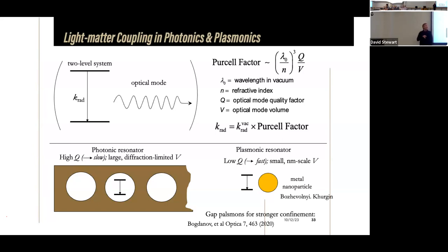But you still need to increase the coupling. And I could accomplish it by beating the diffraction limit, by taking the plasmonic structure, which could easily confine light down to 5 nanometers. 5 nanometers is 100 times smaller than the wavelength. And since you have to raise it to the power 3 because it's volume, it gives you a 1 million increase in the coupling efficiency just because of the confinement. And quality factor is 100. The bottom line is I have the same increase in the coupling efficiency, but if I use a plasmonic structure instead of a dielectric cavity, my system operates much faster, at the rate of 10 terahertz.